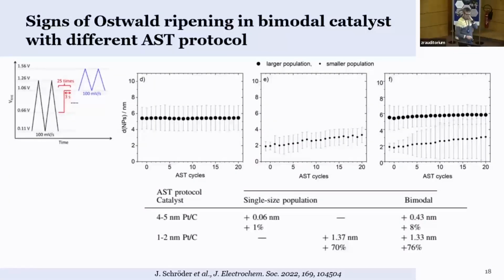And then on a different beam time, we started to change the protocol. So playing around with a protocol that combined different electrochemical treatments. And then with only SAXS, you could see that there's at least a difference if you treat the one catalyst alone or if you mix it. So the large particles under this treatment didn't show any size change. But if you mix them with the small particles, you saw a very small but identifiable size increase in this treatment.